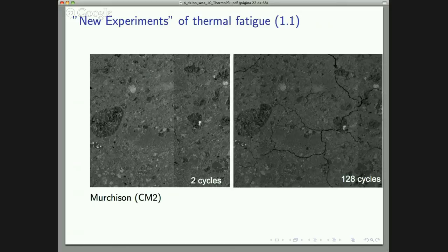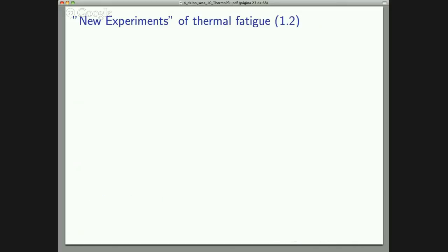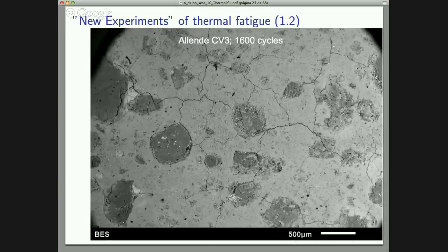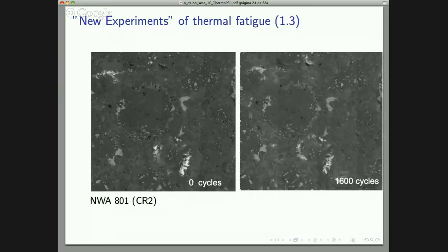And this is Allende, which is a CV3 meteorite. We also cracked it. It took much longer. And surprise, we did nothing to this CR2 meteorite. It's also another carbonaceous chondrite, but we could get no cracks at all. And our interpretation is that the CRs have more metal, and so the metal is ductile and absorbs this strain without producing much stress.